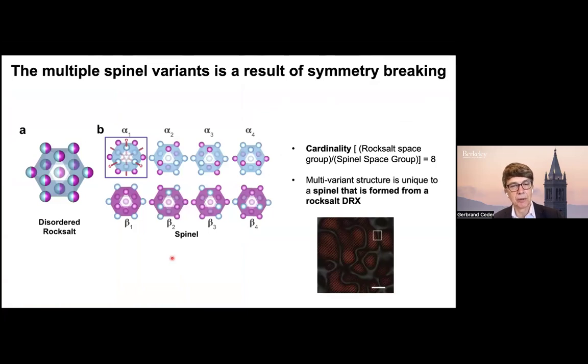I always thought there were 2, but there are actually 8. There's, of course, the variant that comes from translational change, changing the 16C and the 16D site. But for each translational variant, there are 4 orientational variants. So if you take a disordered rock salt and you randomly start to grow a spinel in certain place, and you do that in another place and another place, you will have 8 different variants growing.